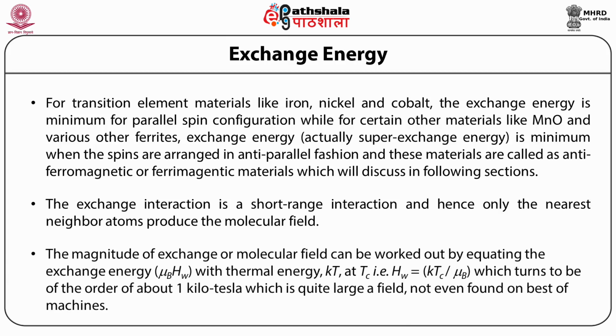The magnitude of the exchange or molecular field can be worked out by equating the exchange energy, that is mu b HW, with thermal energy kT at Tc, that is HW is equal to kTc by mu b, which turns out to be of the order of 1 kilotesla. And as we have previously mentioned, this is a very large field.